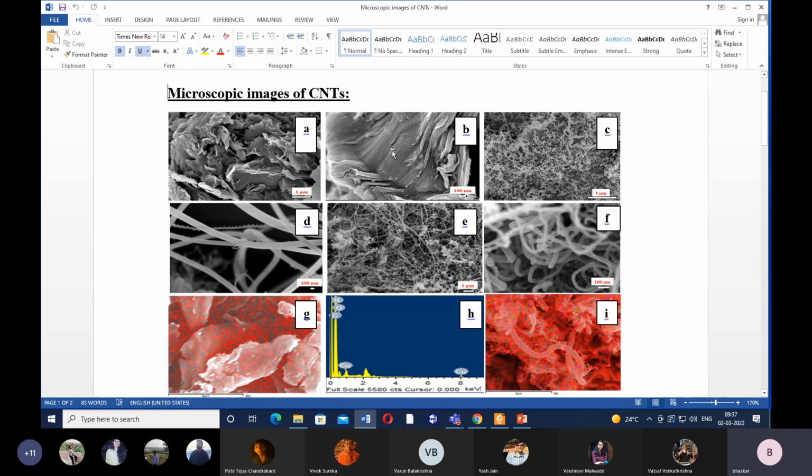Here, this is for the graphite, and after incorporation of copper nanoparticles, I allowed CxHy. In this case, I used acetylene, that means C2H2. So C2H2 came in contact with the copper-doped surface at a temperature of around 350 degrees Celsius for 30 minutes. After 30 minutes, I terminated the reaction.